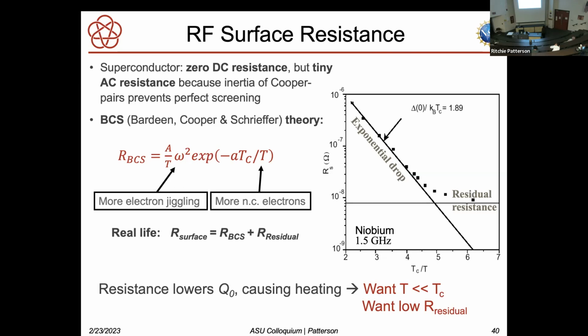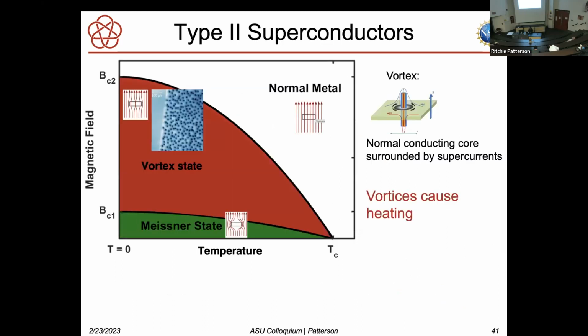Resistance lowers the quality factor of the resonance, it causes heating. And so what we want for good operation is very low temperature and also low residual resistance, or at least we want to operate far below the critical temperature, and we want low residual resistance.